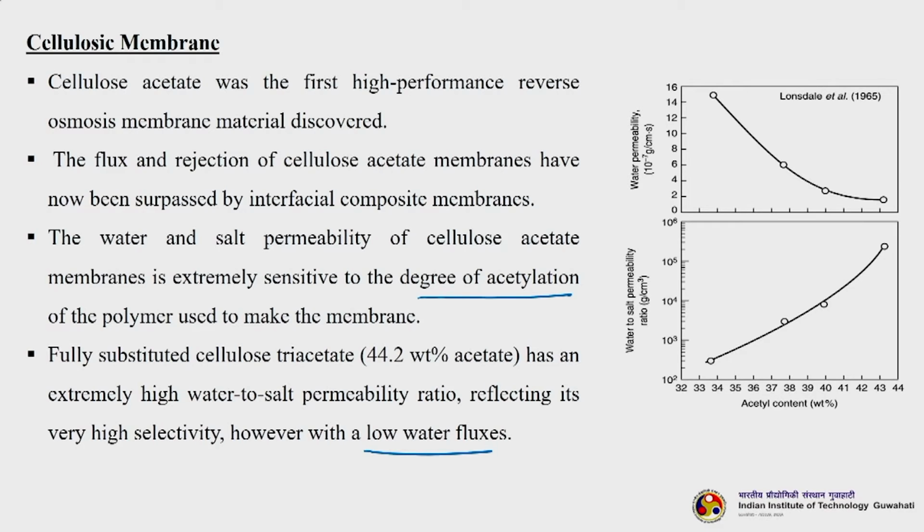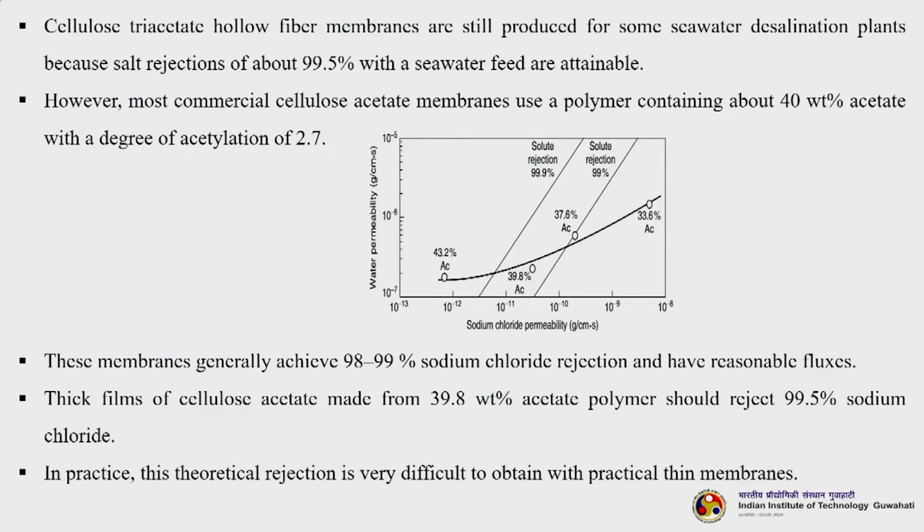So, this is a Lonsdale study in 1965. You can see that water permeability is decreasing here with acetyl content. However, water to salt permeability is increasing. CTA hollow fiber membranes are still produced for some seawater desalination plants because salt rejections of about 99.5% with a seawater feed are attainable.